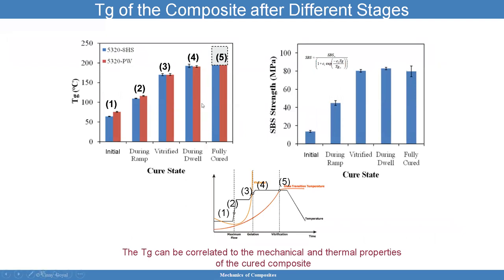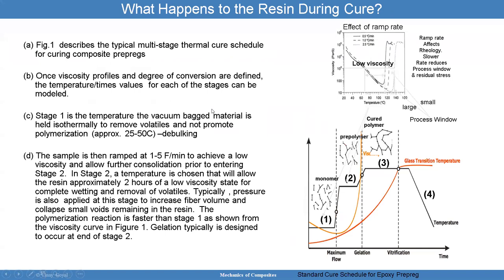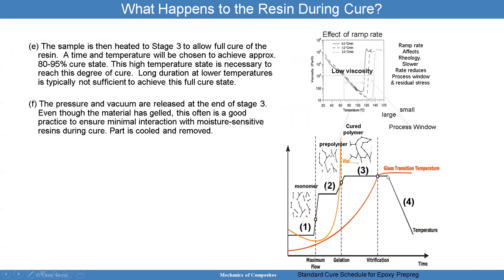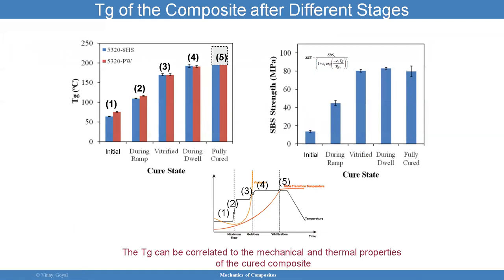So I do want to discuss the TG of the composite after different stages. As I discussed before, that glass transition temperature is increasing as a function of stage. Initially the TG is fairly low. Here are two different materials, basically the same resin, but different formulations of that resin. You can see here that it is increasing and then it achieves a constant state. In this case, the TG is about 180. So when it's fully cured, you've achieved a TG that's going to be that one, as an example.